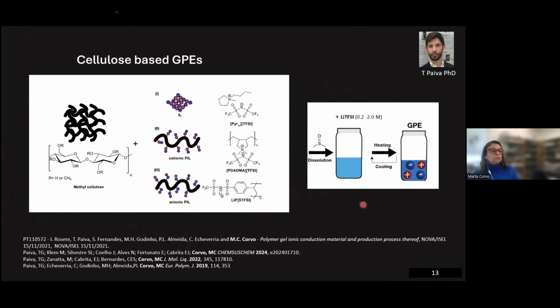And our work started with the dissolution, of course, of the methyl cellulose in the presence of either of these components, and then the use of lithium bistriflamide. This is a lithium salt that is highly used for these gel polymer electrolytes to enhance the conductivity and to bring lithium into the equation. And then we do heating and cooling cycles until the gel is stable. When you do the heating and cooling cycles, you are giving energy to your system, making the system move more quickly, with more freedom. And then when the system cools down, it will revert to a more stable gel. After a few heating and cooling cycles, you get a stable gel polymer electrolyte, and these are our starting materials to go to the micro supercapacitors.